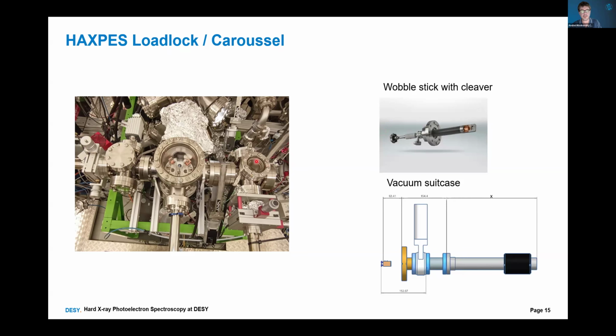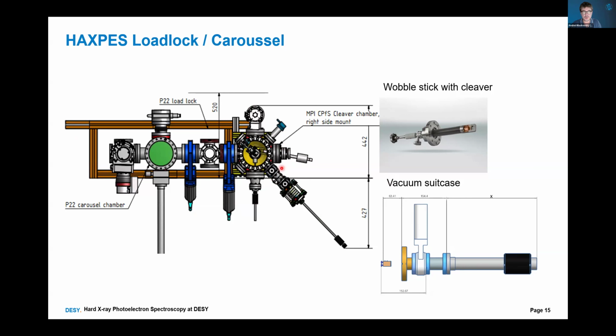We offer also a wobble stick with a cleaver if you want to prepare a fresh surface for your sample. Or if you study hygroscopic samples or solar cells or lithium batteries, which have to be mounted in argon atmosphere, we can transfer the samples in the noble gas atmosphere and dock them to the experimental chamber. Or you, as a user, can come with your own chamber, like MPI did to study uranium samples. They wanted to cleave them, and we of course asked them to come with their own cleaving chamber because we didn't want to have the pieces of uranium in our load lock. So they came, they cleaved their samples, and they removed their rubbish after the beam.